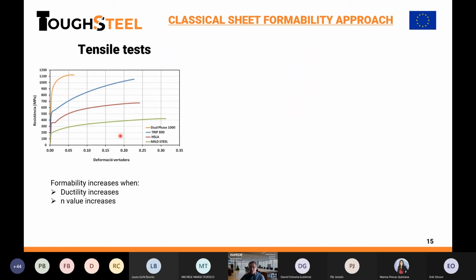The higher ductility is supposed to have higher formability. Increasing the N values, the slope of this range of the curve is also interesting because it allows to homogeneously spread the thickness and then increases formability, reduces neck localization. This is tensile test information.